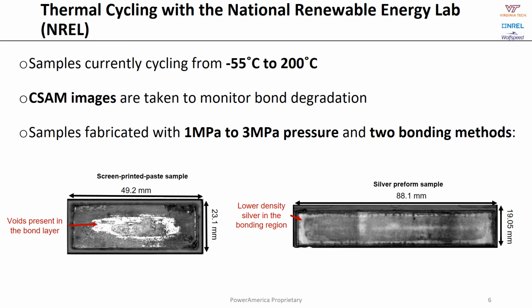So the two processes are compared and samples are placed in a thermal cycling chamber in parallel to monitor their bond degradation and the propagation of any cracks or defects in the bonds by cycling them from minus 55 degrees centigrade to 200 degrees centigrade. And this cycling is taking place at the National Renewable Energy Lab in Golden, Colorado. So CSAM images are taken of the entire group of samples, some made with this screen-printed paste, and some made with this silver preform, both of them using a pressure range of between 1 and 3 megapascals to determine which provides the optimal method for creating samples that are the most reliable.